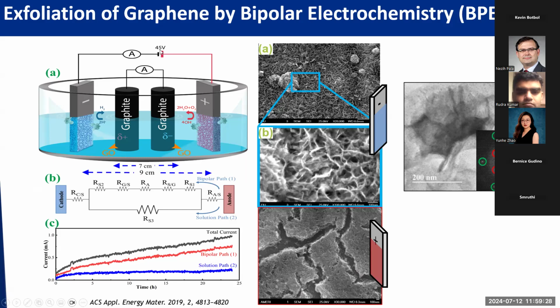The reason is, when you add, in our case, 45 volts into this bipolar cell, the distance between the 2 feeding electrodes is 9 centimeters, so the field is about 5 volts per centimeter. If you change the distance between the graphite and the feeding electrode, eventually you tune it and find a good condition. You can exfoliate the graphite from both bipolar electrodes. At the edge, if this bipolar effect is big enough, the water decomposition will generate bubbles, so you have oxygen and hydrogen at both sides. Those bubbles will be drawn to the graphite, and they can exfoliate graphite. And the ions can be integrated into the graphite at the extreme edges, just near the feeding electrode. Then you can start the exfoliation.